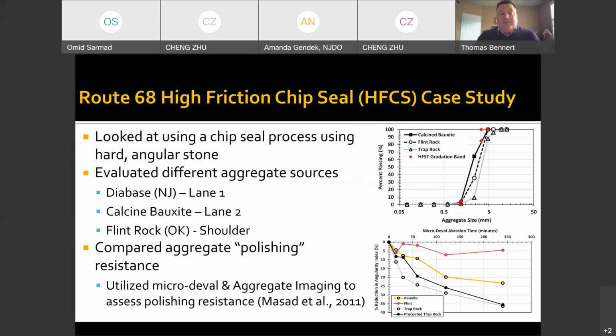And because this was a test section, it allowed us to look at different aggregates, because the calcined bauxite material is extremely expensive. So if we can use more local aggregates, aggregates that are easier to ship in, or just simply less expensive, that would also provide a cost savings to New Jersey and also the municipalities. So we looked at a local diabase. We also included the calcined bauxite, and we also had a flint rock, which is a very hard aggregate from Oklahoma that we had shipped in.